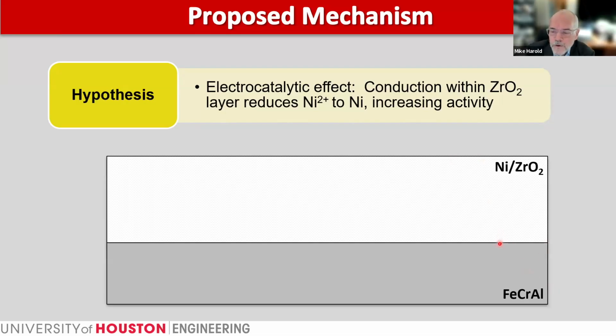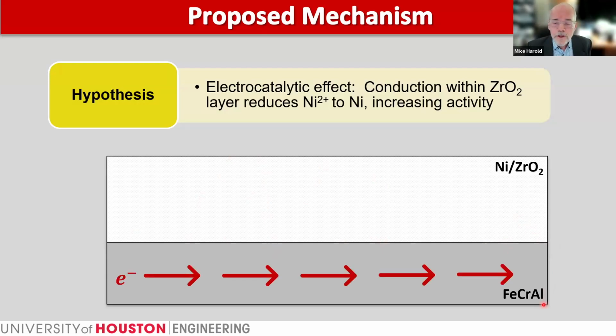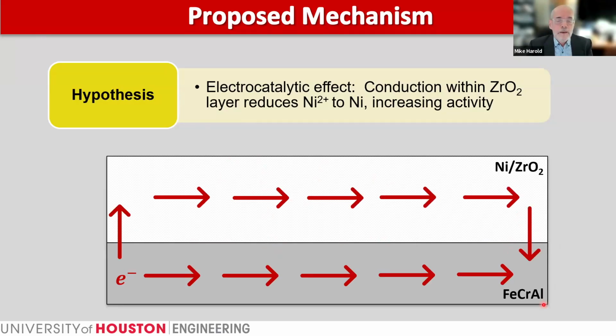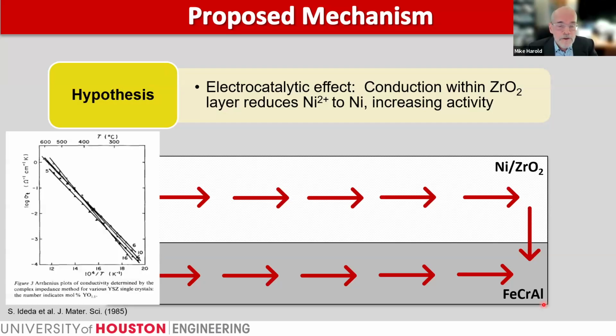So this is a schematic of the interface between the underlying FeCrAl wire and the nickel zirconia. It's obviously not to scale. So this line here is the interface. Again, the thickness of this support layer or catalyst layer is tens of microns. The FeCrAl wire, on the other hand, is about half a millimeter in diameter. So it's a thin layer. Now, under conditions of applied voltage, the electrons are obviously flowing through the FeCrAl because this is leading to an excessive heating of this resistive metal. What we believe is happening is that some of the electrons, to be quantified, are diverted through a nominally conductive zirconia layer that's supporting the crystallites of nickel catalyst. These electrons are interacting with the nickel in a reductive sense, leading to enhanced activity.